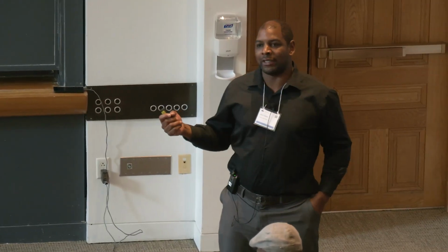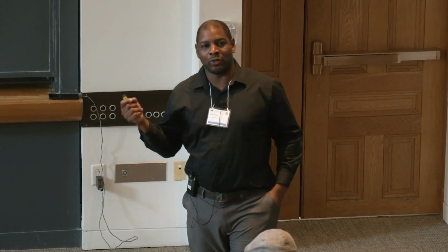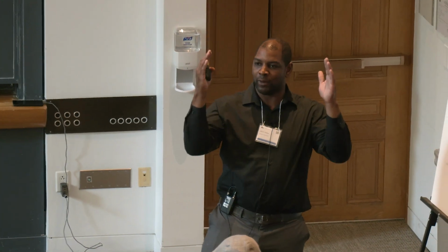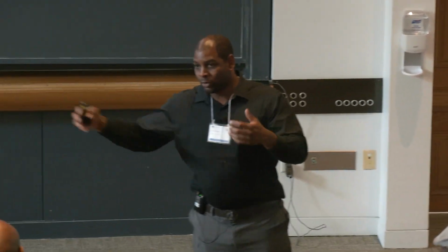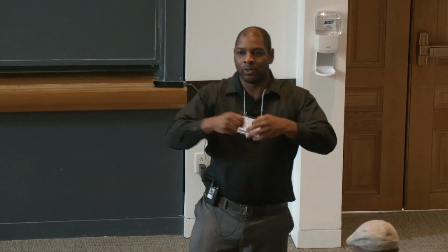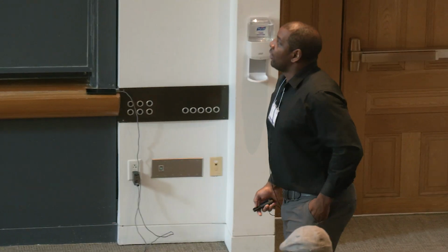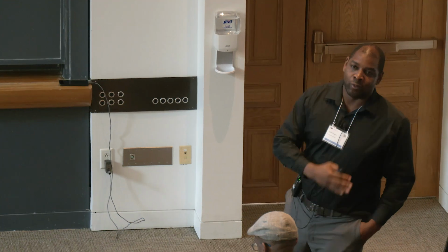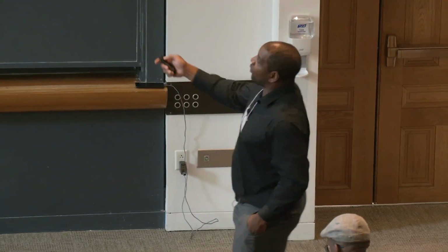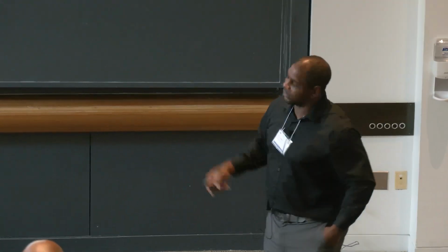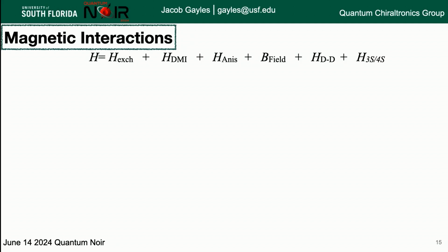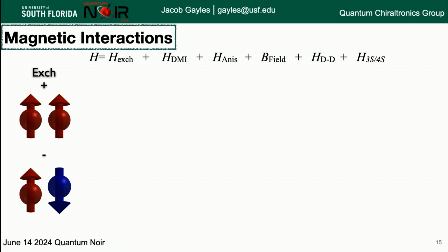Now, what's interesting here is what happens when these two terms compete. One wants things to point parallel or anti-parallel, and one wants perpendicular. What you get is Goldstone modes or spin spirals or magnetic textures that come out. There are other terms such as anisotropy, which wants all the spins to point in a certain direction, or the magnetic field in a similar case. You also have dipole-dipole, and you also have 3-spin and 4-spin interactions, which I won't go into. What it looks like, which I explained earlier, is the exchange, which is a positive exchange, same direction or opposite direction.